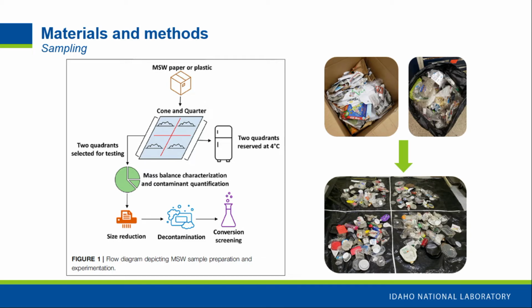So this is an overview of how we did our process. We received MSW paper and plastic. To be more specific, they were actually MRF residuals. And we coned and quartered them on a large tarp that had a quadrant on it, and basically sampled half of the material and reserved half. We then performed mass balance characterization, size reduction, decontamination, and then conversion screening.